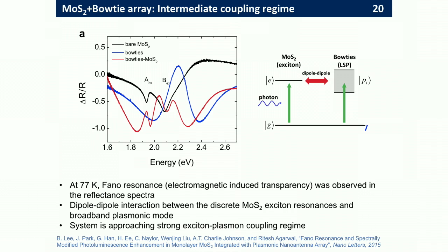Clearly this is not in the weak coupling regime, because in the weak coupling regime we don't change the eigenstates of the system, but now we are changing the line shape of the hybrid system. So this is not real strong coupling, which I'll talk about, but it is telling me that we are moving the system away from weak coupling towards stronger coupling. But this is not strong coupling strictly defined.